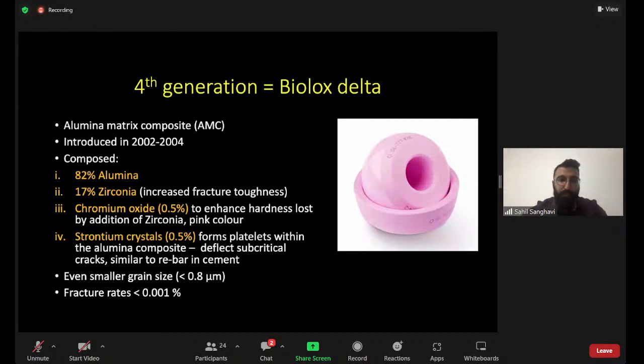as Biolox Delta. This is basically an alumina matrix composite, and it's composed of 82% alumina, 17% zirconia, which was added to increase the toughness. It contains elements of chromium oxide, which enhances the hardness lost by the addition of zirconia. And this chromium oxide is what gives it the pink color of Biolox Delta. It also has strontium crystals, which form platelets within the alumina composite. And the grain size is now even smaller. That is, it's less than 0.8 microns. The fracture rate with fourth generation Biolox Delta is now less than 0.001%, which is negligible.